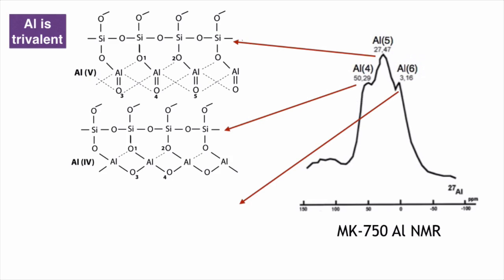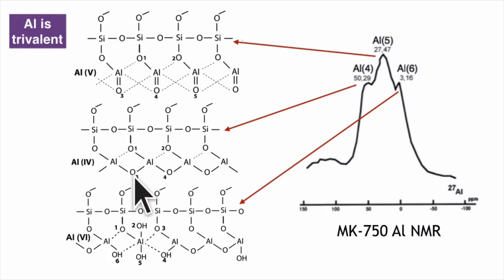Al6, this is the remains of hydroxyls in the molecule. We never get all the water out in Metakaolin. It contains between 10 and 30% of the hydroxyls that are still there. They need more time and higher temperature. And this is the aluminum.